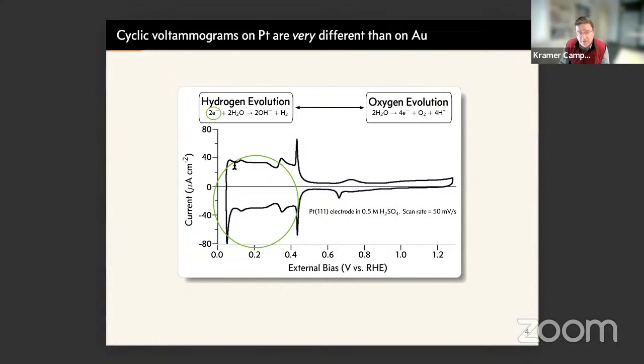If you scan back positively, you oxidize, you desorb hydrogen, and adsorb sulfate as you go back up towards 0.4. So the details here are interesting, and we will come back to some of them. But the 3,000 or 10,000 meter view of the problem I want to offer now is that if you just look at these voltammograms, you can see quite clearly that it will be important to account for the bulk electronic structure of the material. Even if we take two metals, gold and platinum, they apparently, just from the voltammogram, have very different reactivities with respect to hydrogen and oxygen evolution.